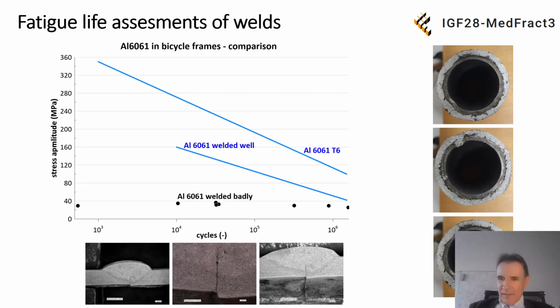We try to assess or test this weld joint. This is a weld joint directly from producers. This is reality, and this weld is relatively simple for us, because to obtain the SN curve for testing was relatively simple. This is a circle with constant thickness of the tube.